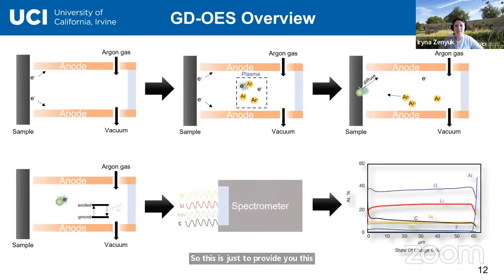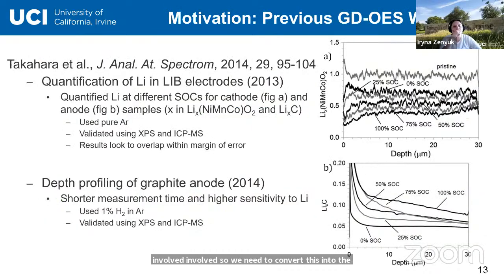So this is just to provide you the overview of how the process works. The final signal that we receive is in volts, so we need to convert this into the atomic percentage of certain elements. If we think about what's been done in the batteries field using glow discharge optical emission spectroscopy, a group from Japan is very active in this field, and they looked at quantifying lithium in lithium-ion batteries, at lithium with varied state of charge.